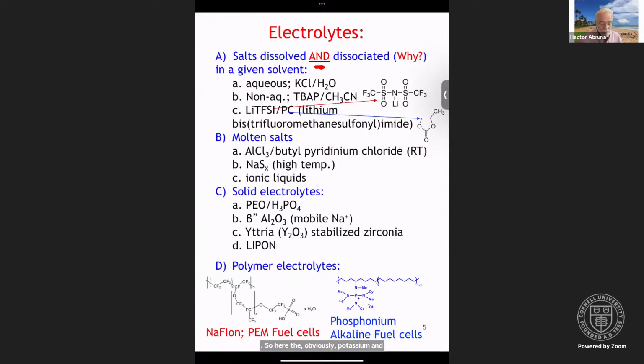You can have a wide variety of non-aqueous solvents. TBAP stands for tetrabutylammonium perchlorate, a very common non-aqueous electrolyte, used in acetonitrile, a very common non-aqueous solvent. As we'll see later on, the advantage of using non-aqueous electrolytes is that it enables a much broader range of applied potentials over which you can have electrochemical reactions. In water, you're limited by the potentials where hydrogen is evolved or oxygen is evolved, so-called hydrogen evolution or oxygen evolution. Thermodynamically, that's 1.23 volts. But because the kinetics can be sluggish and you can play some tricks, you might be able to expand that to a little bit less than 2 volts, in that ballpark.